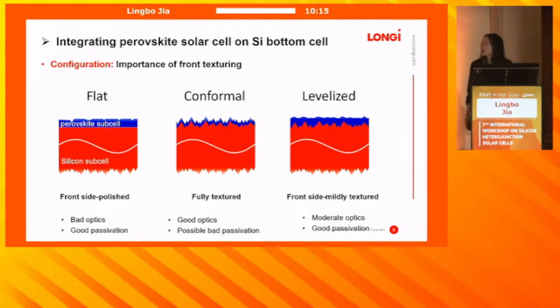So a key challenge for the fully textured perovskite silicon tandem solar cells is how to deposit conformal perovskite layers on micro-sized pyramids. Although this approach can enhance the optical management, it is difficult to achieve good passivation of perovskite films. So a front-side mildly textured silicon design aims to make a balance between moderate optical performance and favorable passivation of perovskite films, which can lead to enhanced device performance.